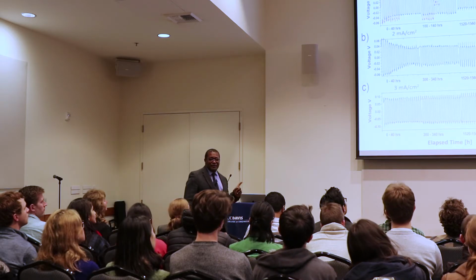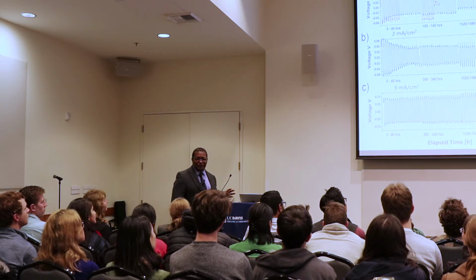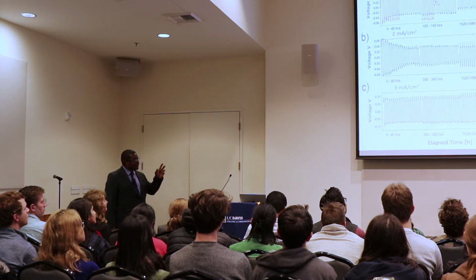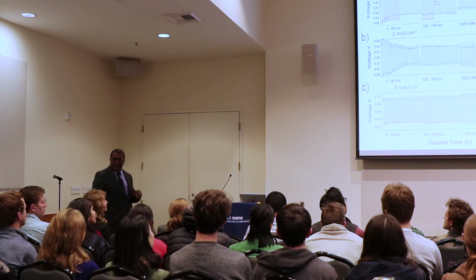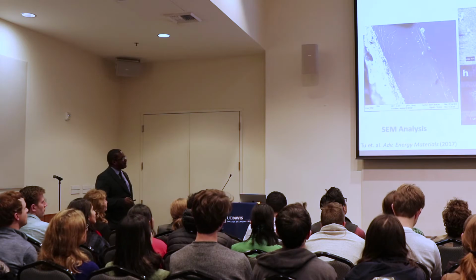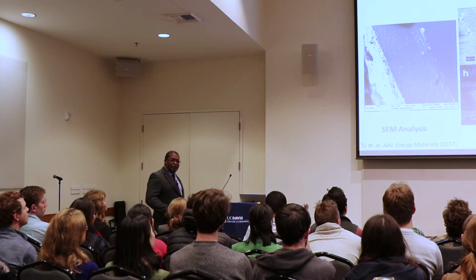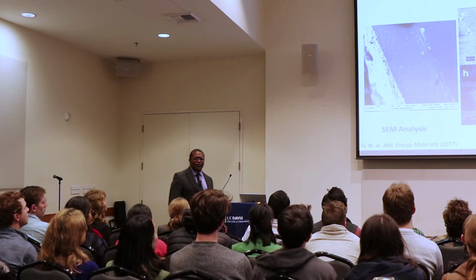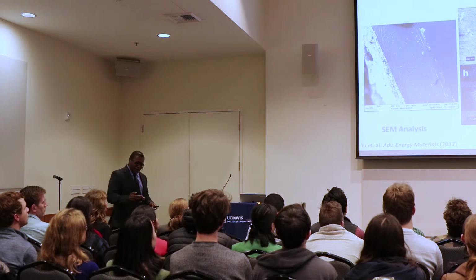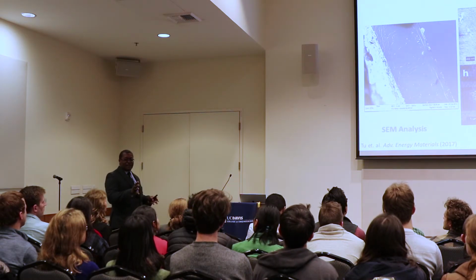And I actually didn't believe this result because it's just too cute—the model says 250 and this failed somewhere between 200 and 300. So I decided to have the student go look inside the pores, because I wanted to know: is there some mechanism where the dendrites might actually grow inside the membrane?